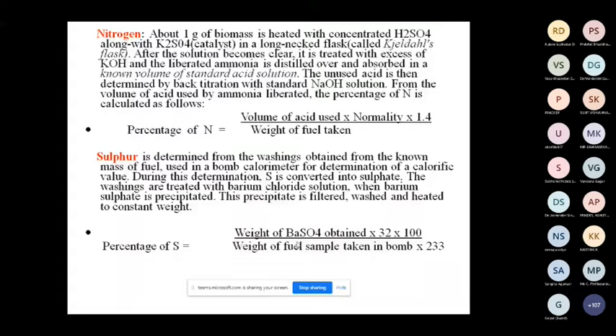Not only biomass fuel, for any organics you can measure nitrogen content by the same method. Then comes sulfur. Sulfur is determined by the old method, the Eschka method. Otherwise, you can do sulfur by bomb washing also. When you are doing calorific determination in the oxygen bomb, all the sulfur will be converted into sulfate, SO3, and sulfuric acid. Then if you add barium chloride, barium sulfate will be precipitated. From that precipitate, you can find out how much sulfur content is in the fuel. So it is called the bomb wash method. Thereby you can measure the sulfur content of the fuel.